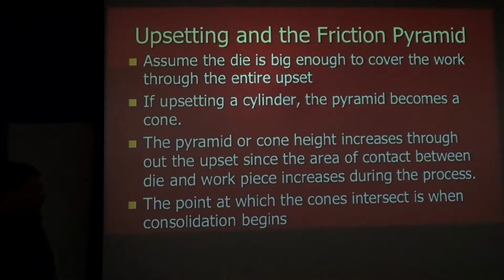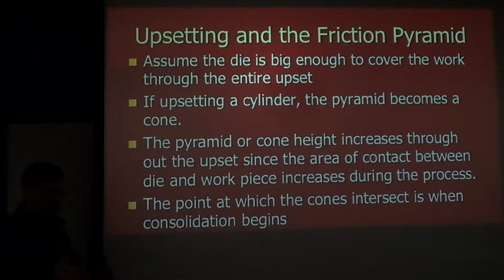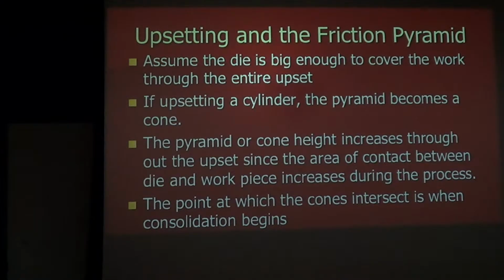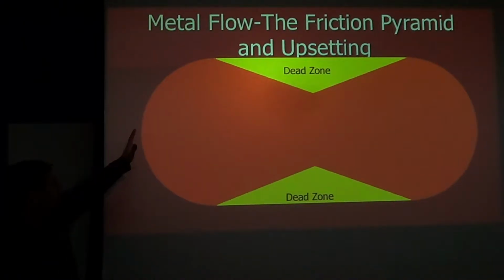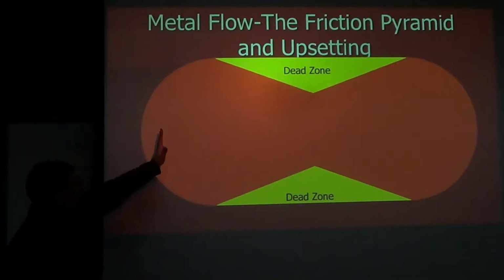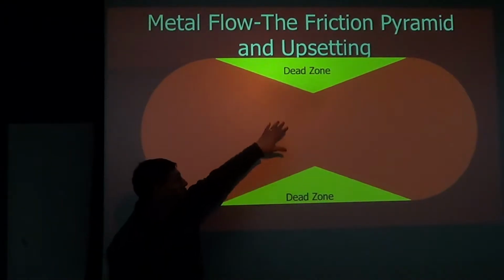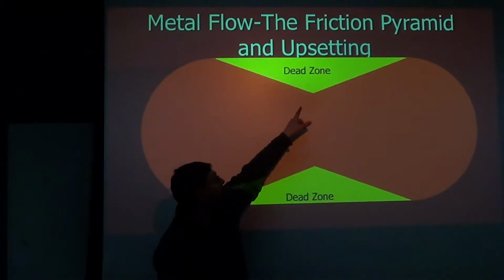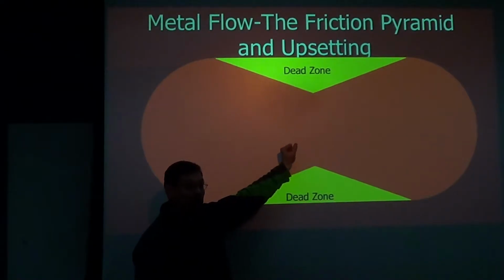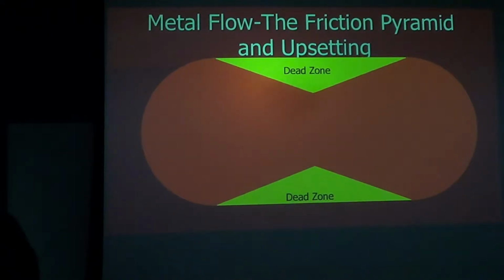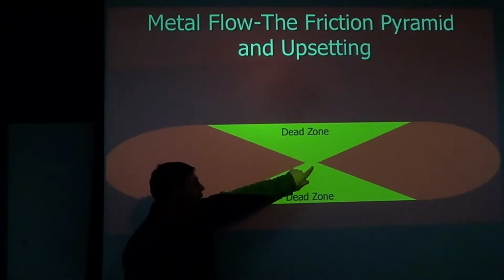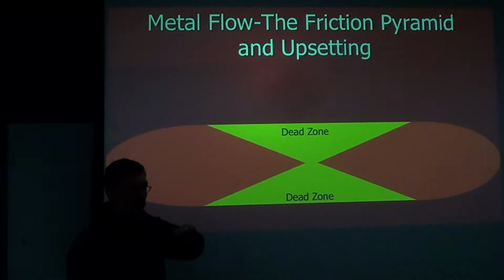Now, the point at which our two cones intersect, if we create a situation where they intersect, that's when we'll start to get the holes to collapse on one another and begin to bond. If we don't reach that sort of critical state, then they won't close up. We'll show that. Here's the initial start of our upset. We've done enough that we no longer have straight sides. We've got some radius, but at this point, my two dead zones are not touching one another. So if I happen to have some holes in here, which I probably do if I'm starting with an ingot, they haven't collapsed. They're moving around, but they're not actually collapsing on themselves. Now, if I keep going, and I get to a point where these two intersect, now I'll start to get those holes to collapse and begin to bond the surfaces together and eliminate the holes.